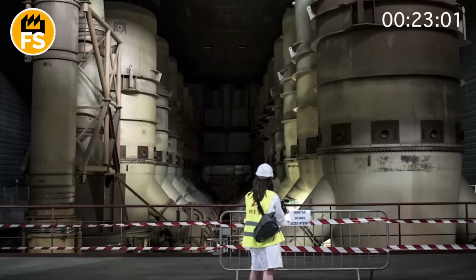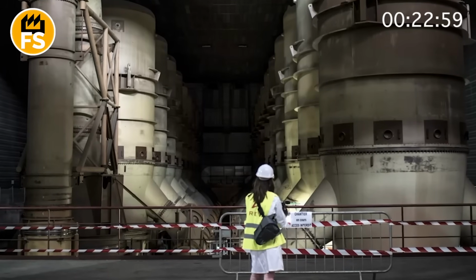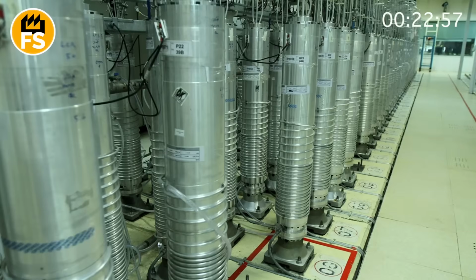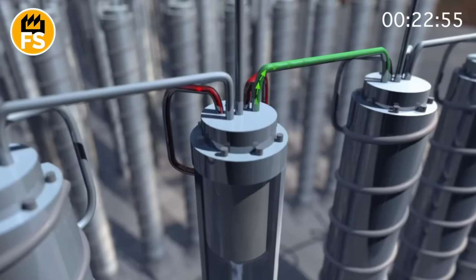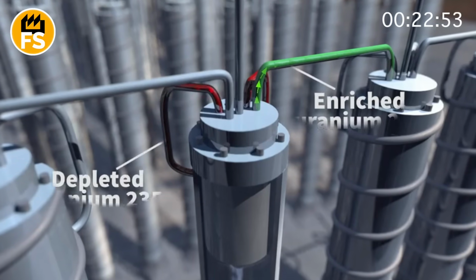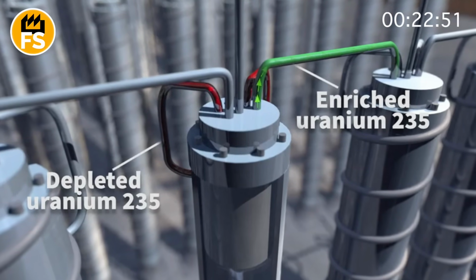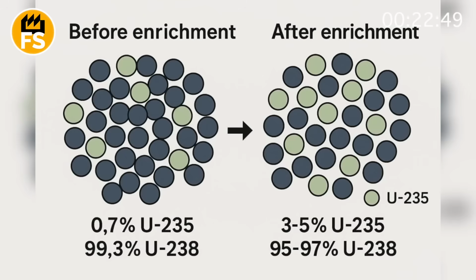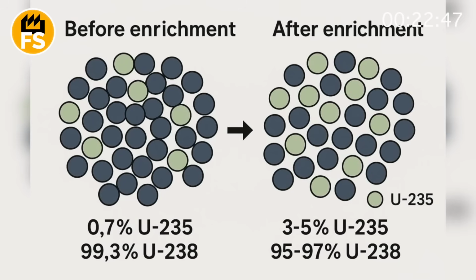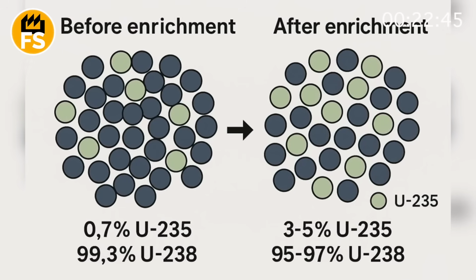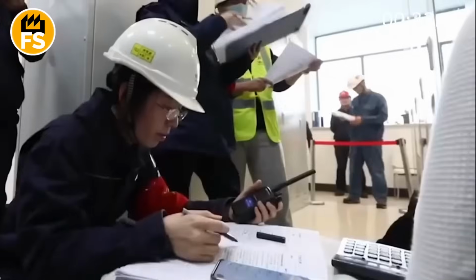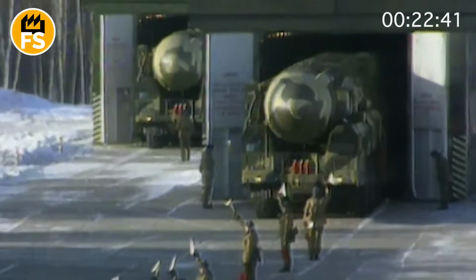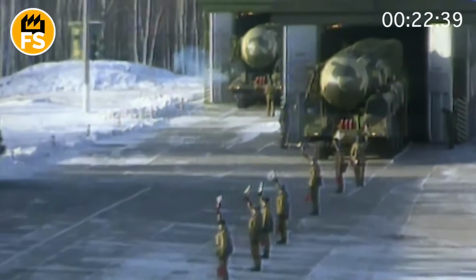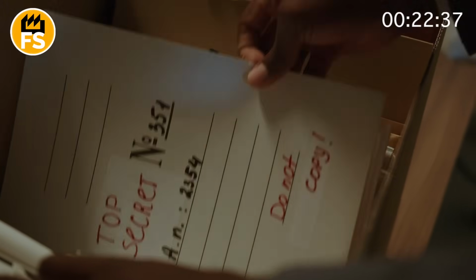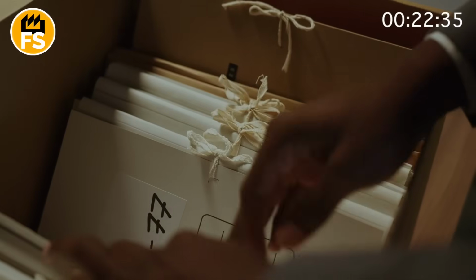But one centrifuge is not enough, so they are connected in cascades of hundreds, sometimes thousands. Each one slightly enriches the gas, then passes it to the next. And so cycle after cycle, until the U-235 content becomes at least 3 to 5%. This is the reactor standard. For weapons, of course, completely different routes are taken. They are classified and under strict international control.